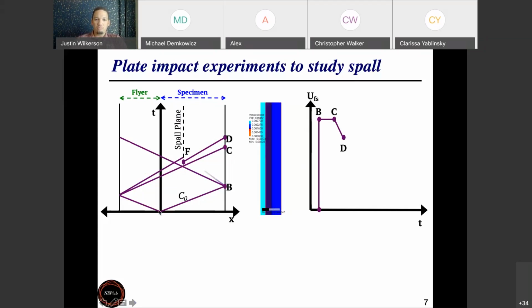So there was a shock wave that moved from the contact surface. It goes to the front face of the flyer plate. It bounces off as a release wave. The reason that they become release waves is essentially you have this material, the flyer plate, in a highly compressed state after that shock wave moves through. But then when the wave gets to the free surface, it realizes what the boundary condition is. And this is a traction-free boundary condition. So if I have a traction-free boundary condition over here, why am I in this highly stressed state? So then it uses that information to send a release wave back to unload the material. And so this is a release rarefaction fan that's coming back. And when it hits the back surface again, then we see a drop in the velocity.